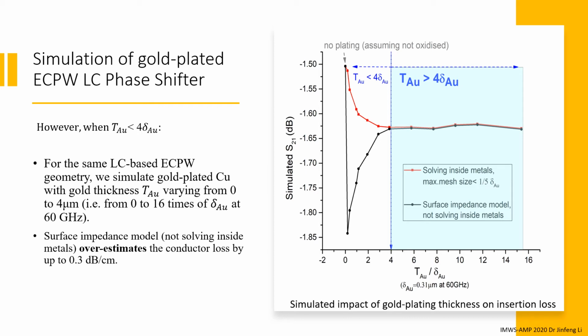S21 levels off when the gold thickness is thicker than 4 times the skin depth, beyond which both models agree with each other in statistics. Furthermore, from this figure, the addition of the gold finish degrades S21 due to the increased resistance as compared with the non-plated pure copper, assuming oxidation has not happened.